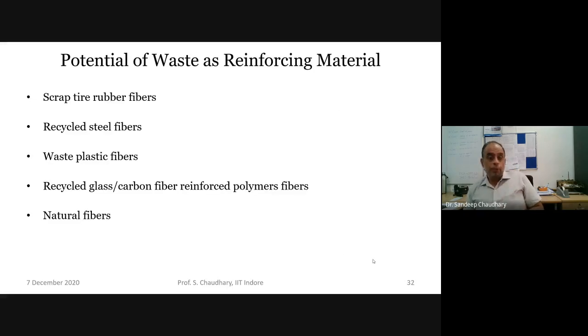We can use the waste as a reinforcing material also, like scrap tire rubber fibers, recycled steel fibers, waste plastic fibers, and natural fibers. And there is again a big misconception here. People think that when we are using these fibers in the concrete, that will increase the flexural strength of the concrete as such. But it's not about the increase in the flexural strength directly. There might be a bit of increase in the flexural strength. But what is important is, whenever we use fibers, whether waste fiber or a fiber which is not a waste, instead of achieving a high flexural strength, what we are looking for is arresting the cracks in the concrete so that it doesn't have an adverse effect on the durability.